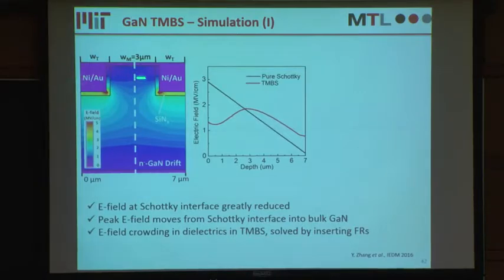So we have the two trenches here, and we have the dielectric here, and this is the gallium nitride pillar, and this is the gallium nitride drift region. If we look at the electric field along this cut line here, then for the conventional Schottky barrier diode, the peak electric field is at the top surface.